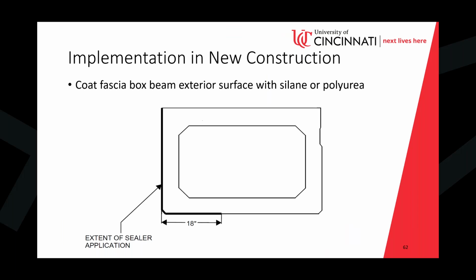We've said a number of times, fascia girders are really your primary issue, especially the vertical face and right below on that, what we think the first 18 inches or so should be protected. So using that polyurea product or a silane or something that can protect the surface, and applying that earlier on, not waiting until it has already started to become a problem before doing that.